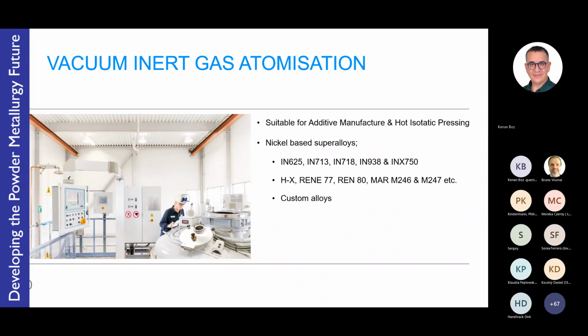It is currently producing a very wide range of different atomized powders in Inconels, nickel-based alloys, as well as more advanced grades like Hastelloys and Rene alloys and MAR-M grades as well. And these are currently being optimized for the laser powder bed fusion process. Some of them are not weldable and therefore present challenges when it comes to producing the appropriate microstructures free from cracks. And custom alloys are being developed. Other alloys include specialist clean materials like INVAR 36.